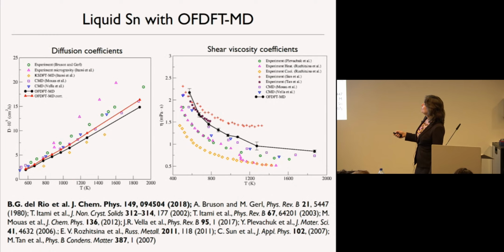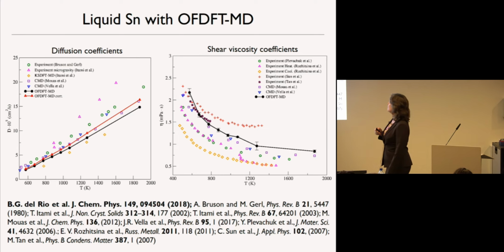Here's more data, diffusivity. We also do well, as you'll see in a moment, with lithium diffusivity. The lines are simulations. The rest is experiment. This is shear viscosity as a function of temperature, and black is our result. So again, we can describe liquid tin quite well with, in particular, non-local kinetic energy density functionals.